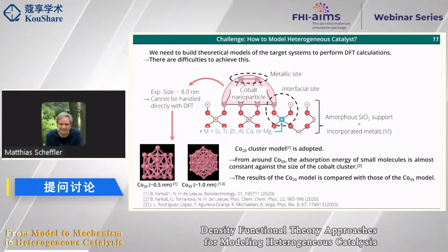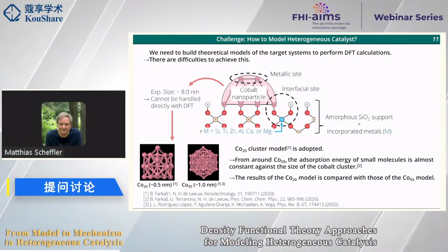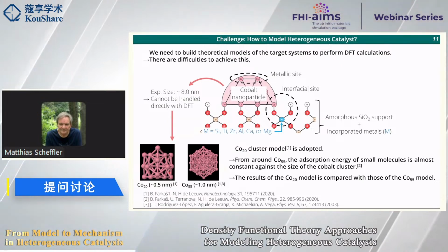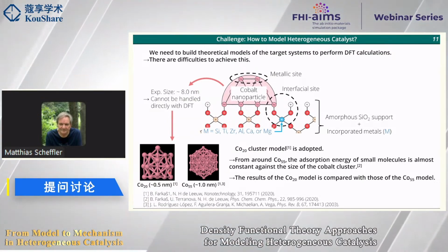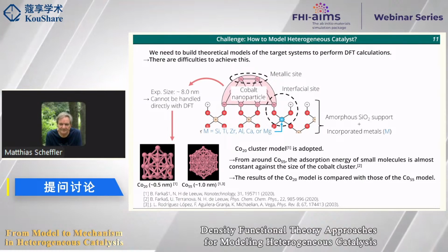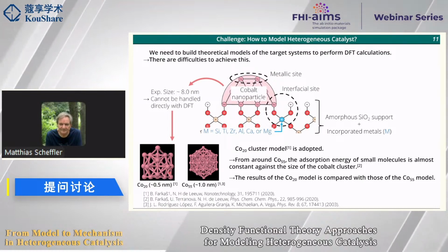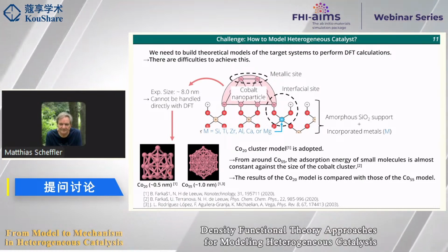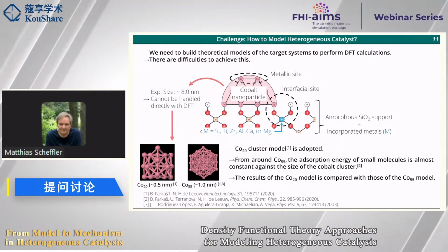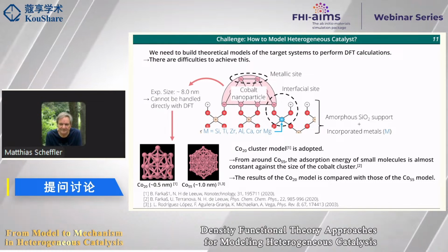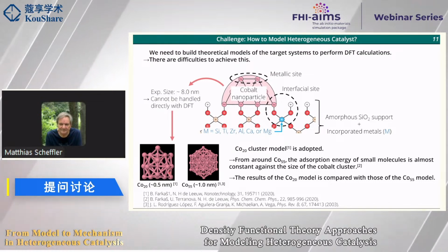Maybe I can add a little bit to that. What we find in general is that the Tkatchenko-Scheffler, which was the very first development, is somewhat overestimating van der Waals corrections. And at short distances, PBE, in fact, already has some van der Waals included, obviously. So in general, if you want to include van der Waals, I think one should go beyond Tkatchenko-Scheffler, and really go to the many-body dispersion to have a more realistic picture.